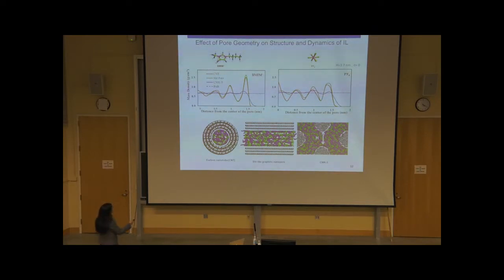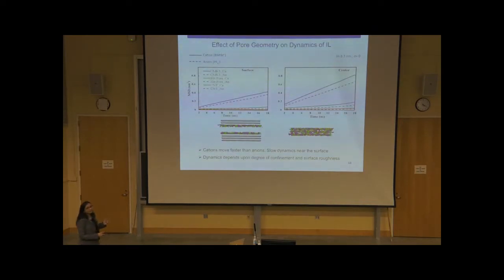But when we looked at the dynamics, and here I divided the mean square displacement into two parts, for the ions which are close to the surface and for the ions which are in the center of the pore. Though we observed similar trends, we found that the dynamics of molecules in the center is much faster compared to the dynamics of ions which are close to the surface. And the trends are the same. We observed the fastest dynamics in the CMK3 model, followed by slit pore and carbon nanotube.